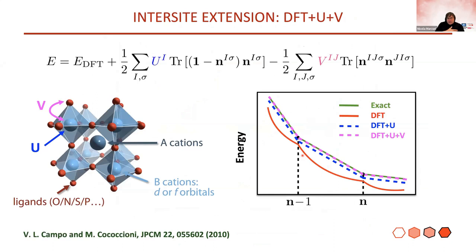Then Matteo kept thinking and actually figured out a refinement that is much smaller but can be extremely important. You'll see in a moment, what he was thinking is that the original rotationally invariant U removes this quadratic dependence, puts back the piecewise dependence, and really tries to restore as much as possible integer traces here, either 0 or 1.